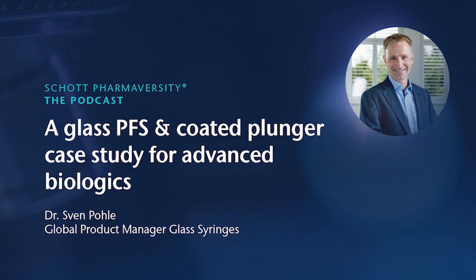And then these elastomer components, closures I mentioned, the RNS and the plunger, they have some permeability, at least the RNS, because it needs to be permeable to ensure the sterilization of the syringes. And here, if it is too permeable, there could be some evaporation and needle clogging appears. Or if there are oxygen-sensitive drugs, there could be compromised stability because of oxygen permeability. And of course, particulate requirements are becoming more and more stringent. So this is, of course, also a challenge for the primary packaging material.